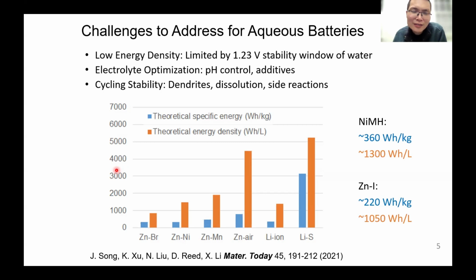So aqueous battery has practically lower energy density, and that is limited by the water stability window, which is smaller than the organic electrolyte. And also the electrolyte tends to change in composition in charge and discharge due to the involvement of water in the reaction. That's another challenge. And finally, the cycling stability in water-based electrolyte is usually lower due to side reactions like dissolution and dendrite formation and water decomposition. So these are the practical challenges.